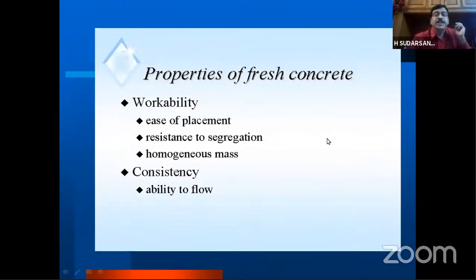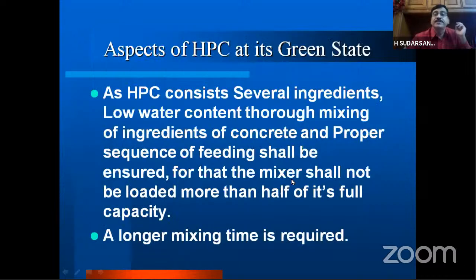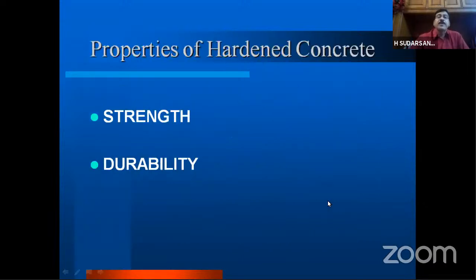Now the properties of fresh concrete: ease of placement, resistance to segregation. This is very important; segregation we should always avoid. The concrete should be a homogeneous mass, consistent, and have good flowability. As high performance concrete consists of several ingredients, and we'll be using a very low water cement ratio, thorough mixing of ingredients and proper sequence of feeding is very important. It shall be ensured that the mixer is not loaded more than 50% of its full capacity, and we may also need a longer mixing time in the case of high performance concrete.